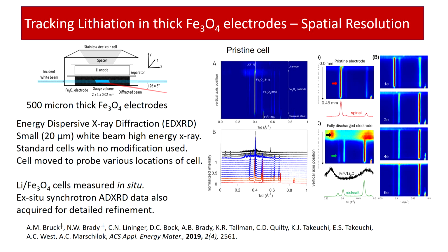So now I'm going to move up length scales again and contemplate tracking lithium and the lithiation through thick electrodes. Ultimately, thick electrodes, if they can be efficiently utilized, will contribute to high energy density batteries, as well as possibly scalable batteries. We use a tool called energy dispersive X-ray diffraction. This is a synchrotron method where we use a 20 micron beam, then move the battery through various locations in the electrode so we can map the progress of the reaction through the thickness, as well as different areas in the XY direction to see how the reaction is progressing.